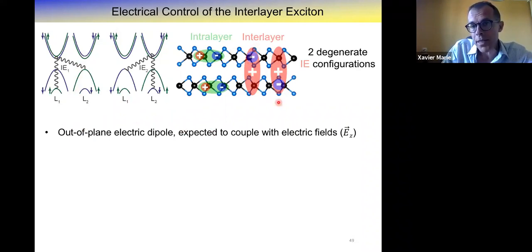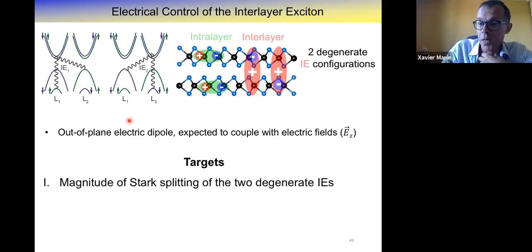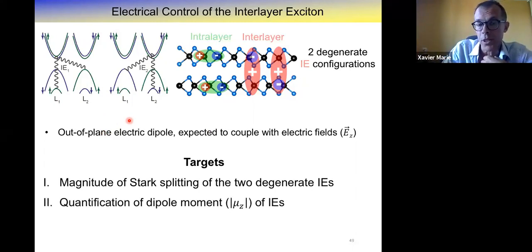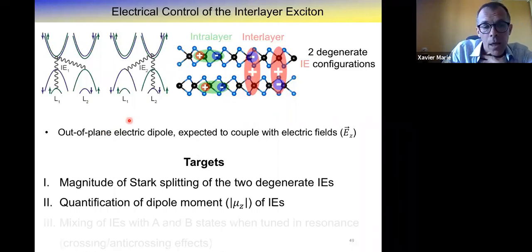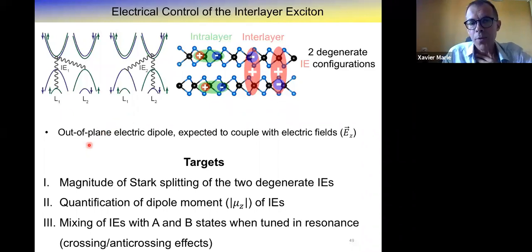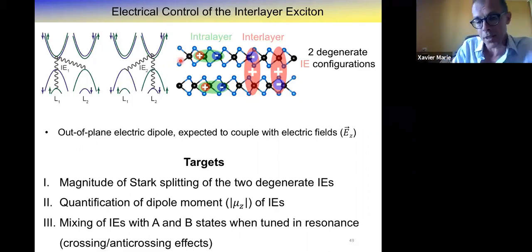As I said previously, you remember the interlayer exciton is, in our view, composed of a rather delocalized hole between the two layers and a localized electron either in the bottom layer or in the top layer. So this means that you expect to have an out-of-plane dipole. And if you apply a Z electric field, we should be able to control and manipulate this interlayer exciton state. And so the motivations are: what is the magnitude of the splitting we can get? We will lift the degeneracy between these two interlayer excitons and try to quantify this dipole moment. And also, if we push the electric field further, we would like to see if we can tune the interlayer exciton in resonance with the intralayer exciton, and then investigate this exciton-exciton coupling.